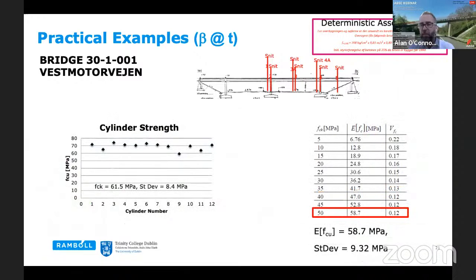So as was indicated by Fabrizio, in terms of the in situ testing which can be performed, in situ tests were performed to assess the strength of the concrete by taking cylinders from the structure. Using that information, as Dimitris pointed out, we were able to update our characterization of the concrete strength to give us revised values for the mean value and the variability associated with that mean value, which we consider in performing the probabilistic analysis of the structure.